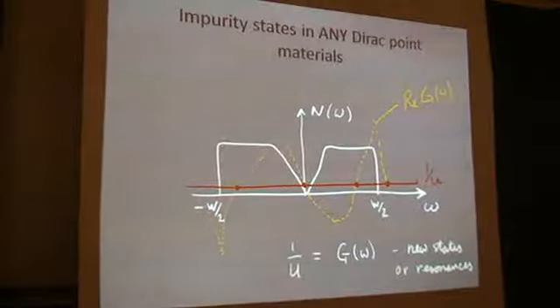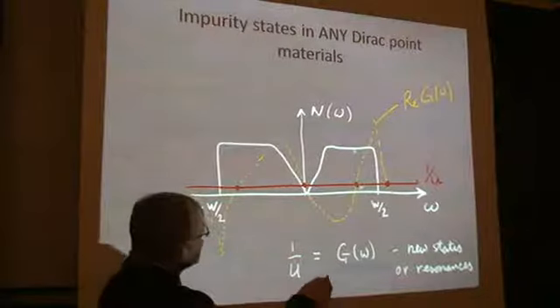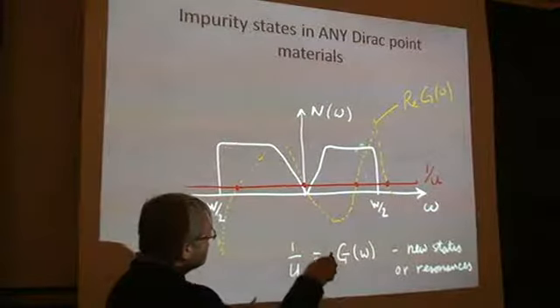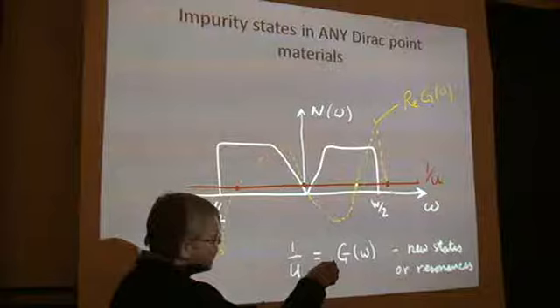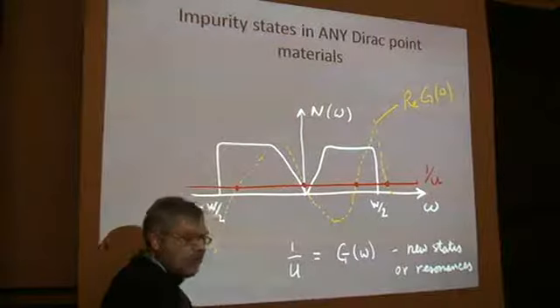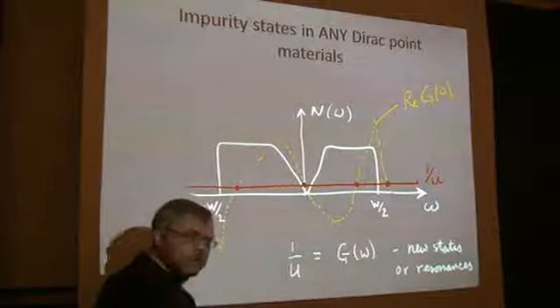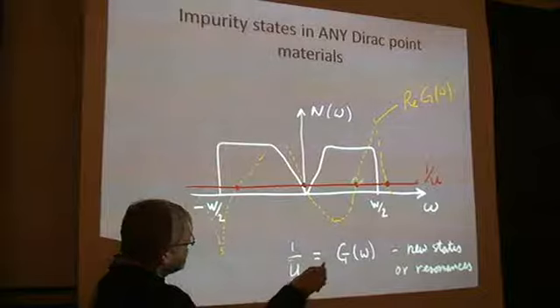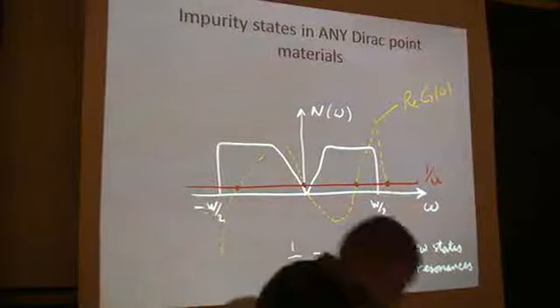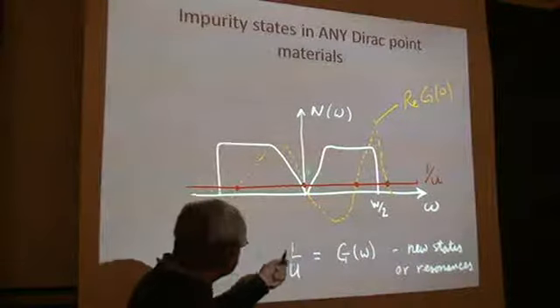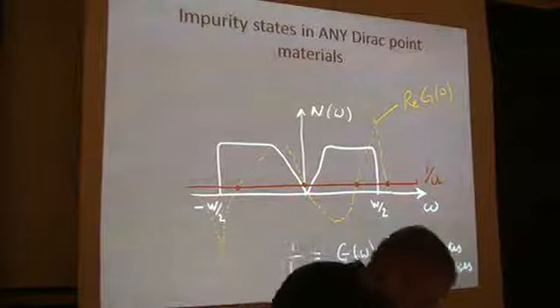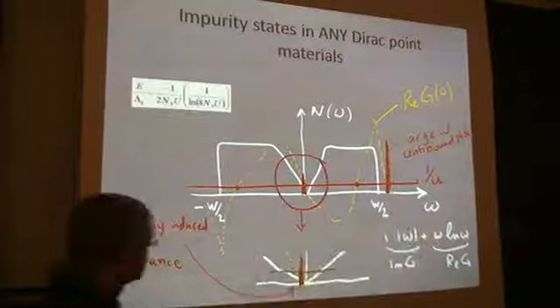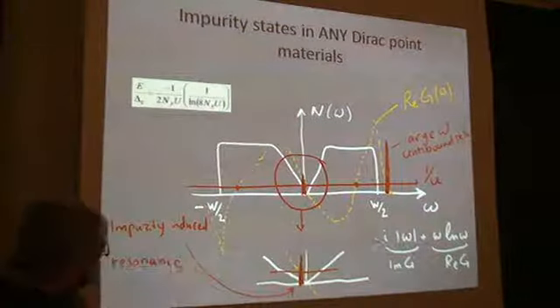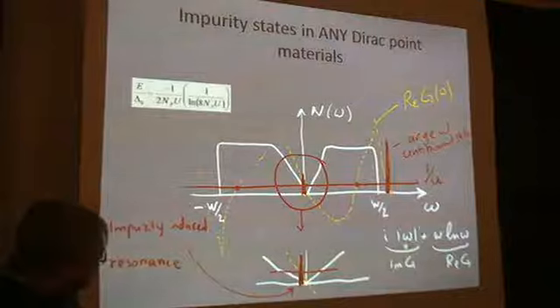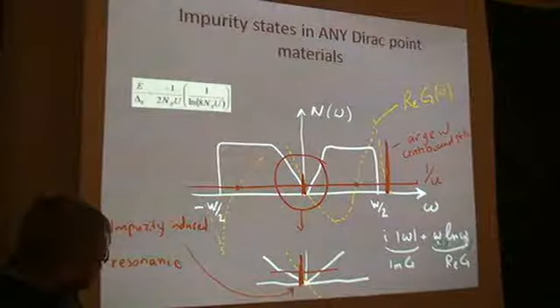The harder the impurity is, the higher energy state it generates. So this crossing point here shows that you have much more of imaginary part in the solution than the real part. Namely, you have a resonance inside the very nice high density of states continuum. And so this solution will be very broad and relevant. And then actually this is our impurity state right here, which is forming as a result of the following. So you have imaginary part inside this notch goes like absolute value of omega, then by Kramers-Kronig you get the real part going like omega log omega.